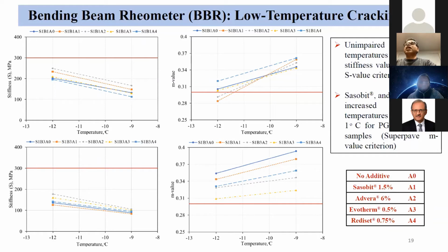0.300. Even from our previous studies, we also found that 1.5% reduces the M value. So for Sasobit, that is kind of detrimental. But Evotherm and Rediset make the binder softer, which is better. Overall, the BBR test results did not have any significant effect.